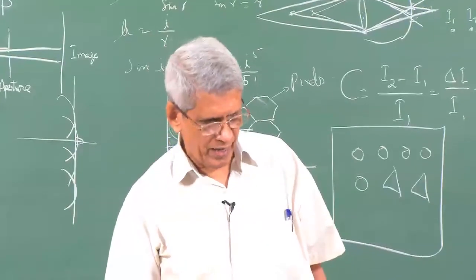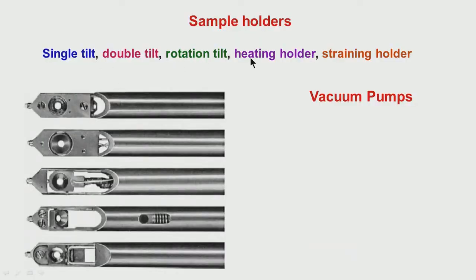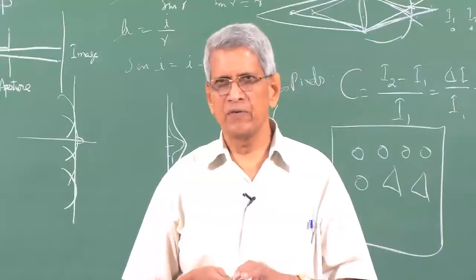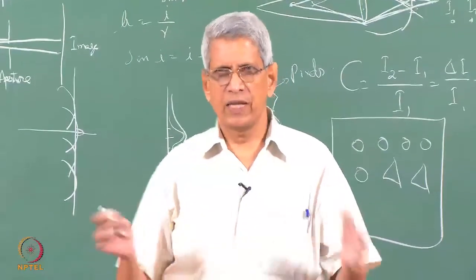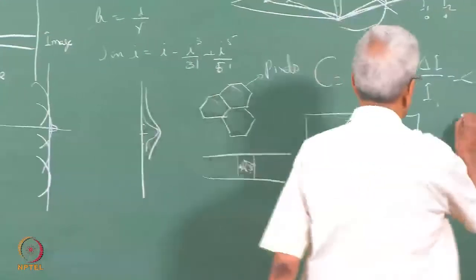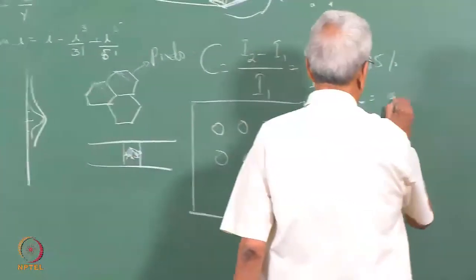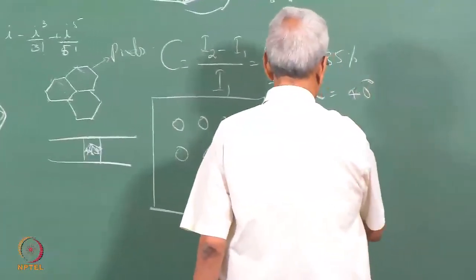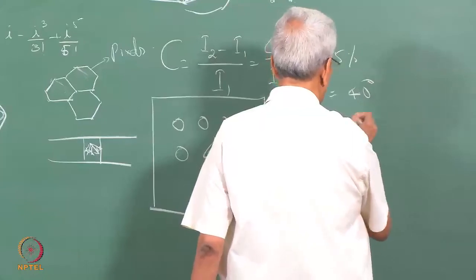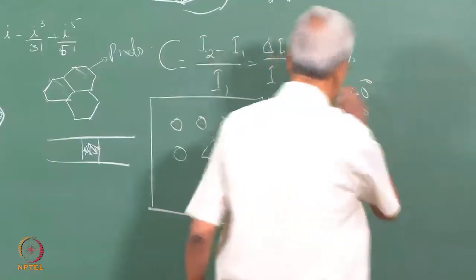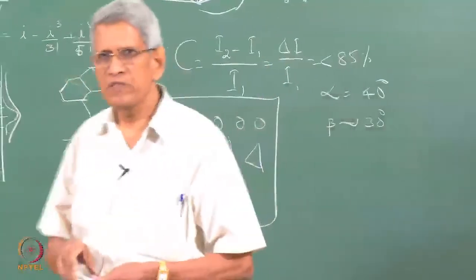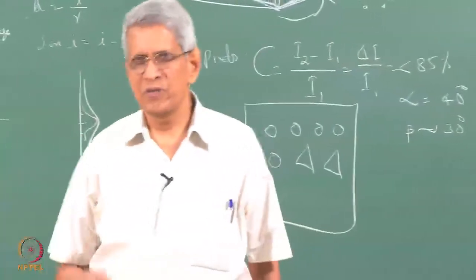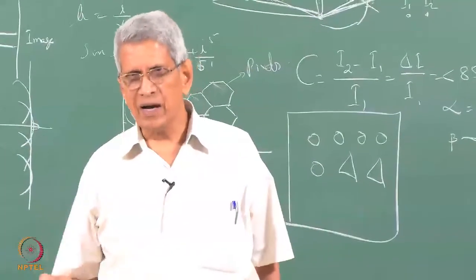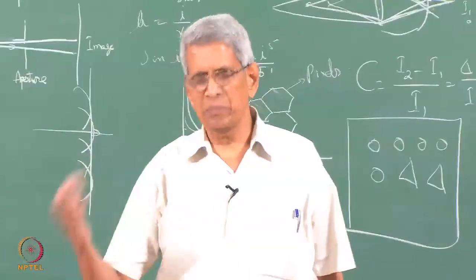And keeping a sample in a double tilt or a rotation holder, depending upon the tilt availability, we can orient that sample in whichever beam direction we want within the limits. Normally, the tilt given in a microscope is about 40 degrees for one tilt, and the other tilt, they call it beta, is of the order of 30 degrees. This tilt covers most of the zones which we want to see in conventional typical cubic materials.